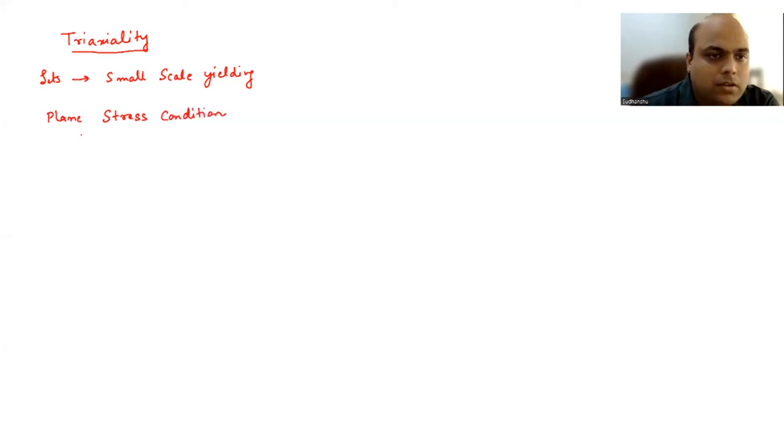okay. So we will now apply the Tresca criterion for yielding, which has been discussed in part one. The Tresca criterion says you have sigma max minus sigma min equal to sigma y, right? Where sigma max and sigma min are the maximum and minimum principal stresses, and sigma y is